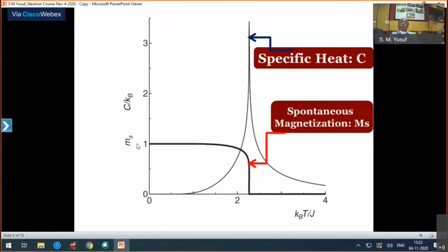By the way, when we say spontaneous magnetization, it is not atomic. If you go a little deeper, the concept is already built in. It arises out of the entire system, like a cooperative phenomenon, like you already know about magnetic domains and this kind of situation. When you cool the specimen to this particular temperature, your spontaneous magnetization builds up. So magnetic ordering takes place, and this order parameter, which you can call the magnetic order parameter, builds up from 0 to this value, and then obviously at lower temperature it saturates. So the order parameter is 1, fully ordered.